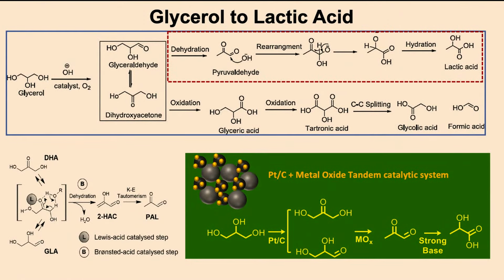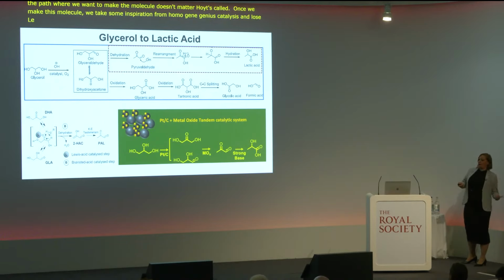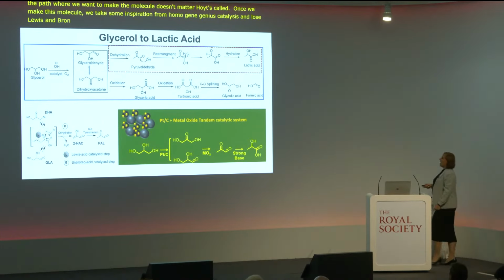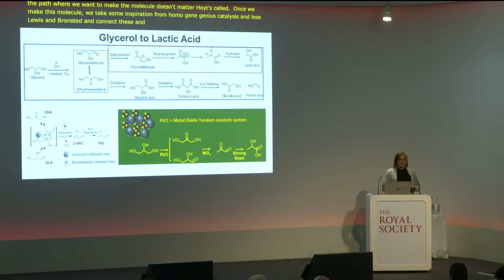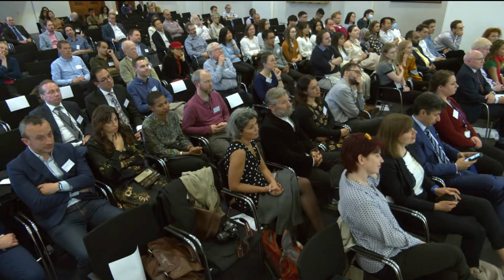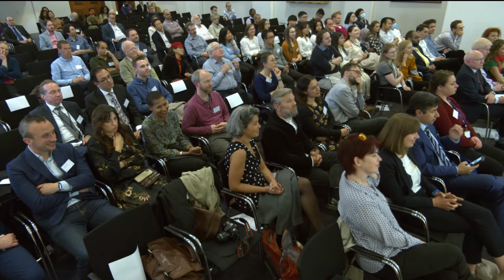So the way it works is she's using glycerol, which is a waste from the biodiesel industry, and there's two paths to oxidizing glycerol, and we want to follow this path, which we want to make this molecule, doesn't matter how it's called. And once we make this molecule, we take some inspiration from homogeneous catalysis, and we use a Lewis acid step and a Bronsted acid catalyzed step. So we combine electrocatalysis with homogeneous catalysis, and we produce lactic acid. It's great to produce lactic acid. You may have all heard of polylactic acid. You probably have all been annoyed with the biodegradable bags for our biodegradable waste, which melt before you take your garbage to the bin. So that's polylactic acid. Well, you could make it better than this.